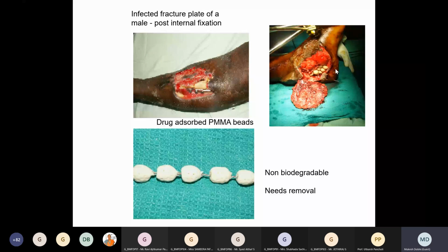If you have a polymer which can prevent this problem, that means the polymer should degrade slowly, starting between the third week and fourth week, and then finally get bioresorbed. Then the surgeon does not have to do another surgery to remove the PMMA type of polymer, which is not biodegradable. So we looked at different types of polymers which can be loaded with the drug, release the drug in the first 10 days, and after 10 days slowly start biodegrading or bioresorbing. So in the next month or two it should completely disappear.